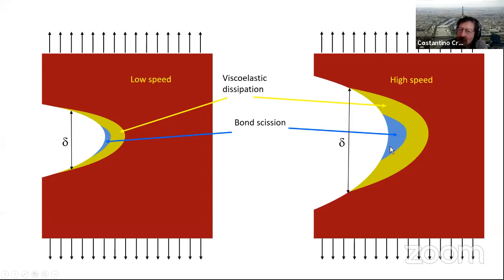So the probability of breaking bonds then increases. And of course, the highest stresses are still close to the center. So you're going to have a regime here with high stresses. Now, in this type of material it is not really a point singularity. You have a singularity in the propagation direction, but in the perpendicular direction, it's not really a singularity. So you have a region of high stresses and high strains, and these high strains increase the probability of breakage. So the picture we have is that there is a synergy between the viscoelastic dissipation, which slows down crack growth and forces you, for a given speed, to increase the opening, and this increase in opening dissipates energy to bond scission. And I think that this is a reasonable view.